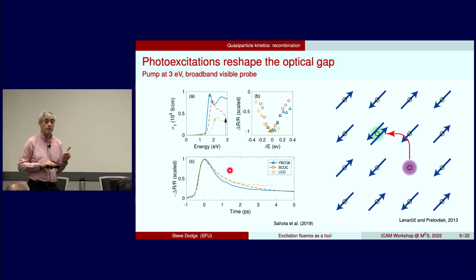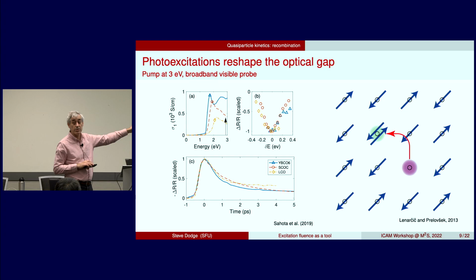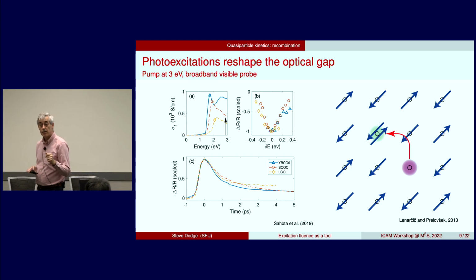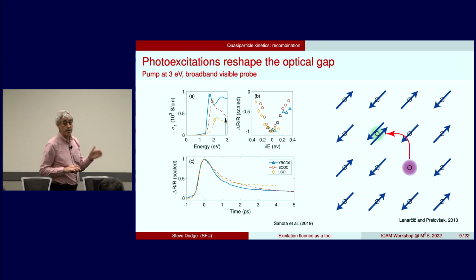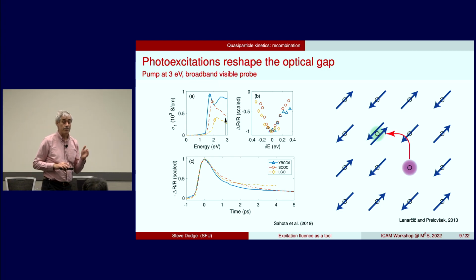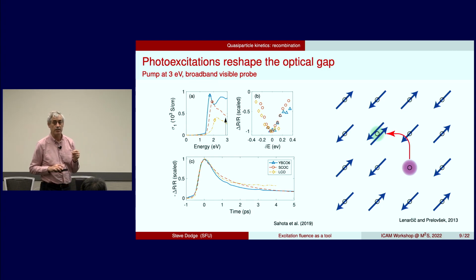And that's the puzzle. Look at the energy scale here. You're giving up 1 to 1.5 eV of energy in less than a picosecond. And if you are giving that up to phonons, say 50 meV phonons, then you've got a lot of phonons to give off in a very short period of time.